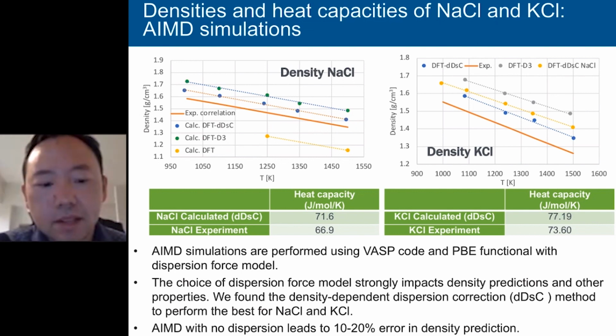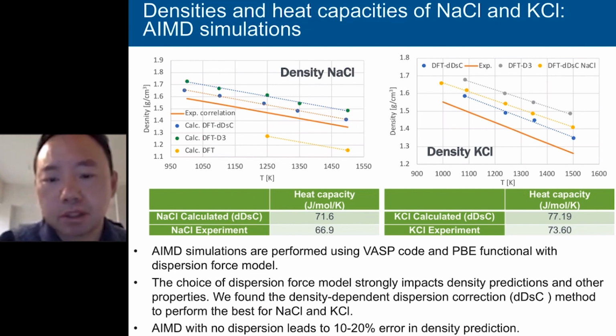So that's the method David suggested for all the subsequent Ab-Initio studies. And the tables below the two figures show the heat capacity of these two salts calculated using the DDSC method. You can see that the agreement with experiments is excellent for both salts.